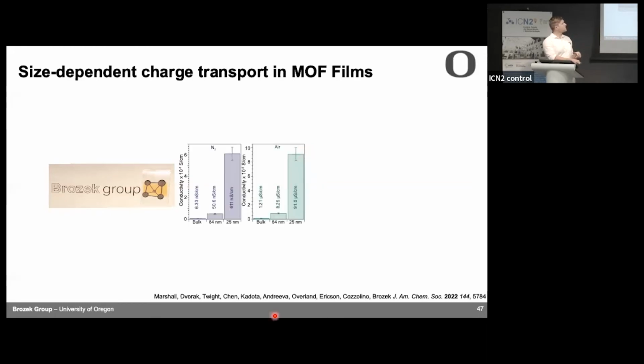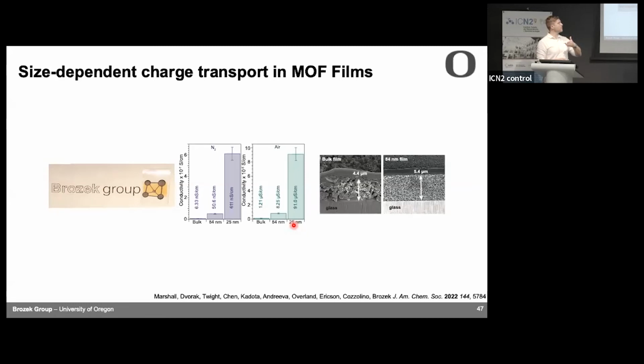And so here I'm comparing thin films of different sizes in nitrogen and air. The particles need to be oxidized in air to be conductive. So in air, everything is about 100 to 1,000 times more conductive. But what was really surprising is that the thin films of the smallest particles are much more conductive than the bulk powder. We were wondering why. And so we took the films, cut them open, and looked at them by cross-sectional SEM. And it looks like, in contrast to the bulk particles, the smaller particles are just sticking together much, much better. There's much less open space. And so basically, particle to particle conductivity is much better.